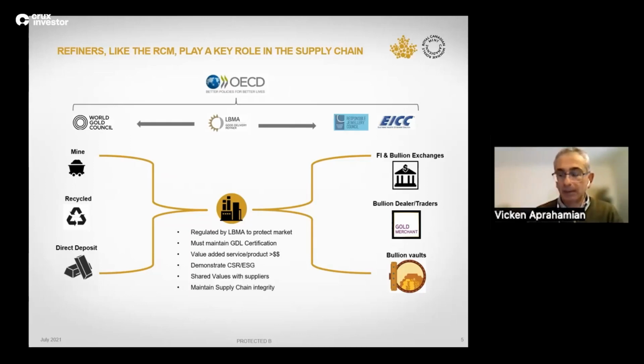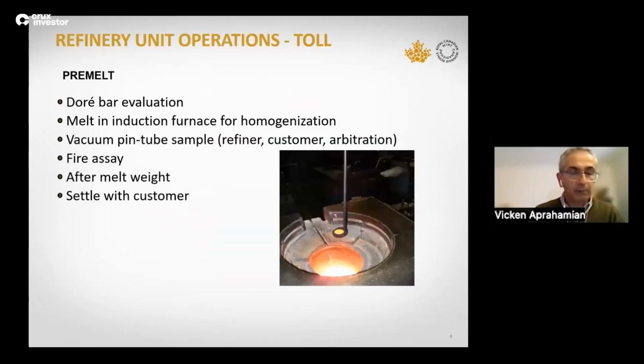So I'm going to move on to unit operations in a toll refinery, which receives bars from various customers. The very first step is to evaluate the material that comes through the door. The standard procedure is what is called a pre-melt. So each bar is taken and is melted in an induction furnace. As the gold melts, it's homogenized, and it allows the taking of a sample. The sample is usually drawn out using vacuum pin tubes. There are 3 that are taken, so in triplicate: 1 for the refiner, and then 2 additional ones, 1 for the customer and 1 for arbitration in case of a dispute.